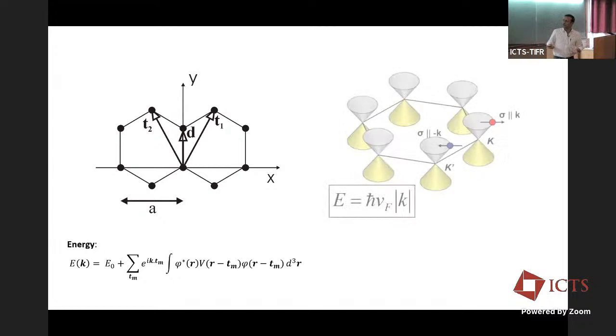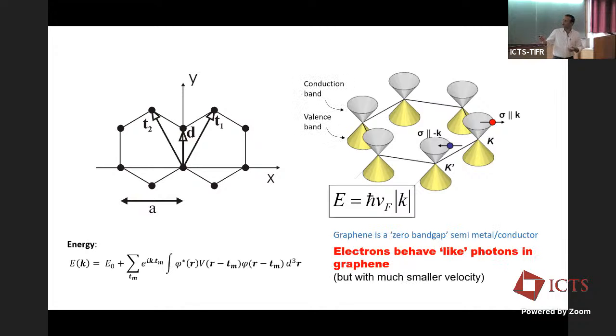So essentially the idea here is that the low energy bands in this kind of lattice look like a linear dispersion with energy, where each point on the Brillouin zone has a cone, and as a result, you have the conduction band and valence band. The conduction band is completely empty, and the valence band is filled. It's like a zero band gap semiconductor or semi-metal. And in addition to that, the electrons behave like photons in graphene, but of course with a much smaller velocity than light, about 300 times smaller.